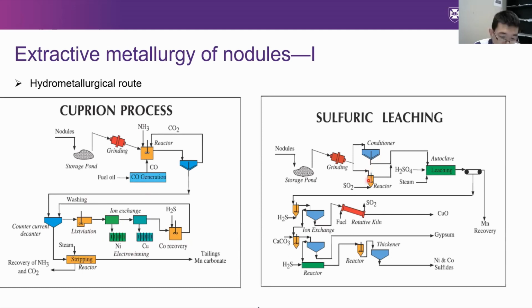And from the right figure, in the sulfuric leaching process, again the nodules are ground to fine powders, and then leached by sulfuric acid in the autoclave at a high temperature and several atmospheres of pressure. Then the copper, nickel, and cobalt are precipitated from the resulting solution by hydrogen sulfide. The copper sulfide is roasted to give pure copper oxide, while the nickel and cobalt are just kept as sulfides. So here it is noted that the hydrometallurgical route is found to be difficult for recovering the manganese from the nodules.